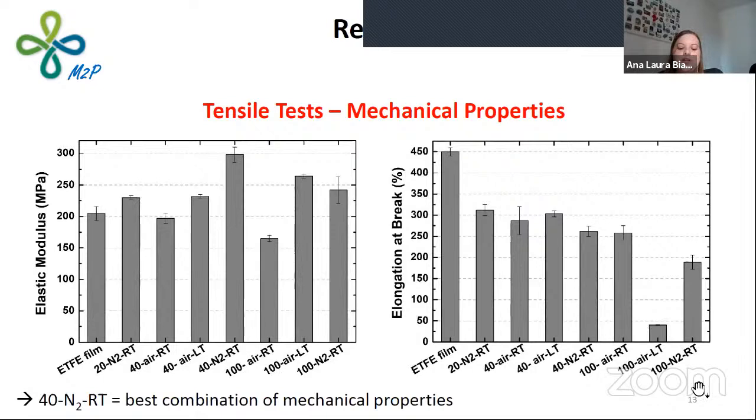See, if you compare with the others, the elongation at break is very low, showing then that highly grafted membranes can become rigid and therefore too fragile to break. So it's not interesting for the application. We have high IEC, but then it's too fragile.